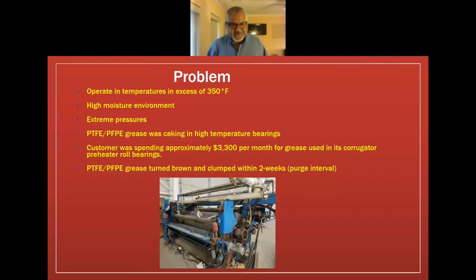The higher temperatures. So the PTFE, PFPE grease was caking in the high temperature bearings. That's why a 2-week grease purge was required. The customers are spending about $3,300 per month for grease used in the corrugator and preheater roll bearings. The PTFE, PFPE grease turned brown and clumped within 2 weeks. So that's their purge interval. It'll still move, but the clumpiness, what does clumpiness generate? Generates heat.